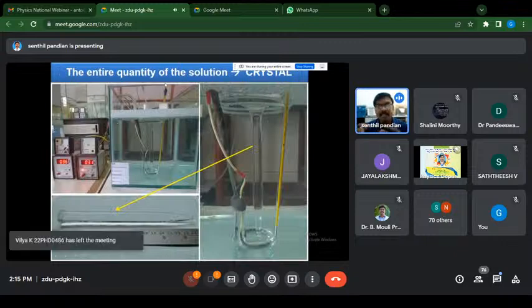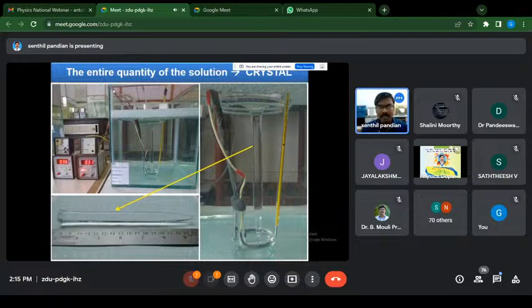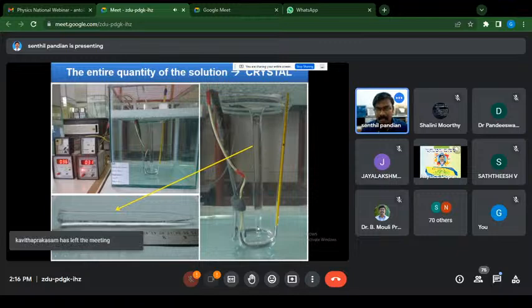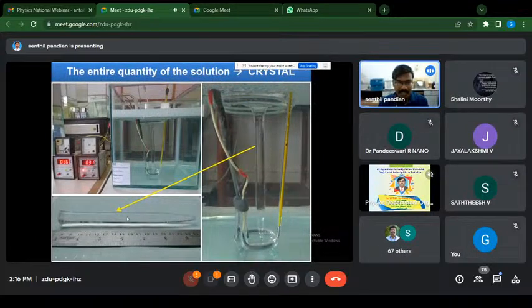So 100% solution to crystal convertibility is possible in this SR method. The entire quantity of the solution is converted into the crystal. You see the seed crystal is mounted here along its polar B direction. The crystal started growing here and ends here. The total length of the grown crystal is around 20 centimeters. You see there are no micro cracks and no milky opaque regions in the SR method grown crystal.